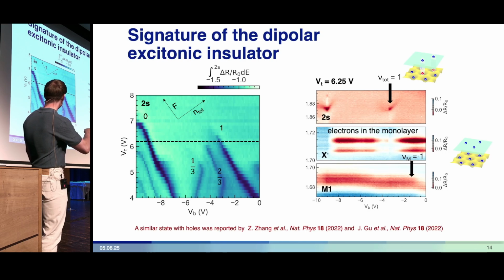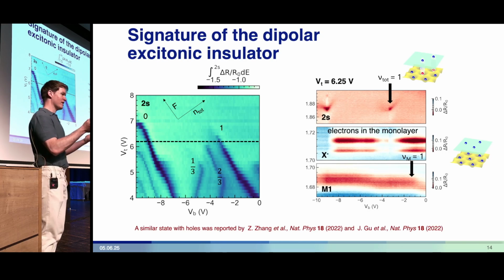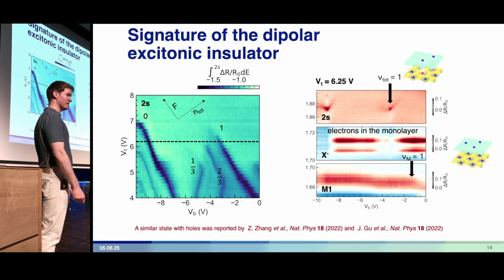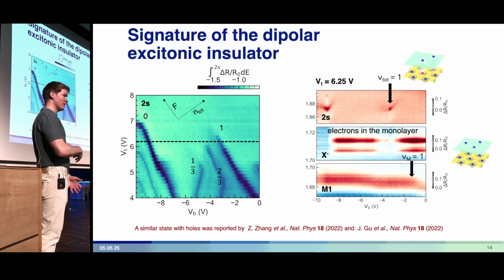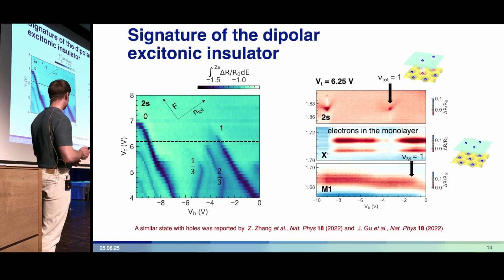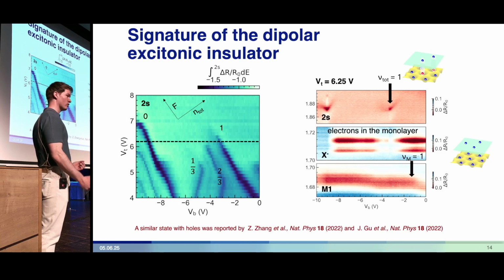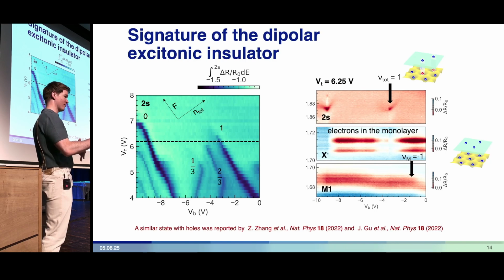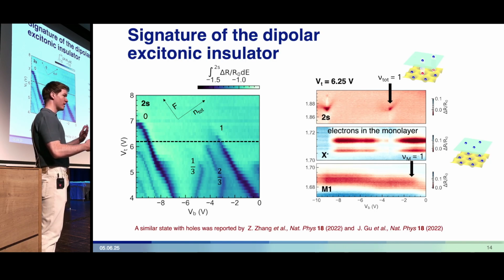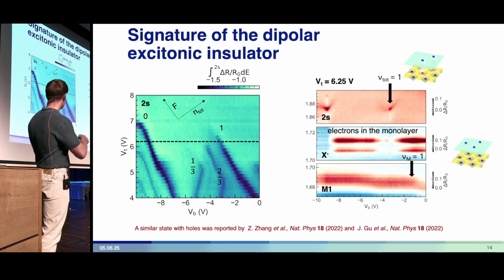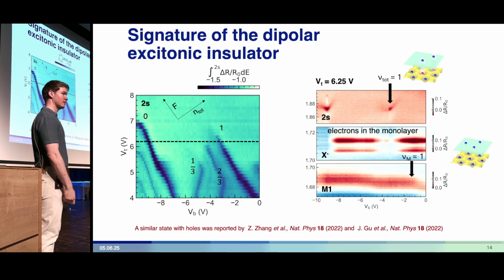If I take this diagonal, or whatever the calculated diagonal should be, it's actually not going to correspond across the phase diagram to density. Calibrating the density is really not straightforward, because we have Schottky contacts, because correlation affects open gaps—correlation gaps—which mean there's some energy penalty to cross it. So there's really not a linear relationship between some linear parameter in this direction and the density.